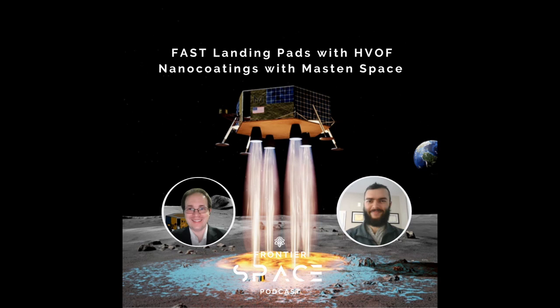Operating in the combustion chamber definitely influenced the materials we chose. That's one of the reasons we went with alumina. It's such a wonderfully inert material. It's an alumina ceramic, not aluminum the metal. If you use aluminum metal, it'll actually combust, and they use that in solid rocket engines. But the inert alumina ceramic powder is just a wonderful material. You can get it in very small grain sizes, and then it doesn't like to interact or oxidize much as you're going through the combustion environment.